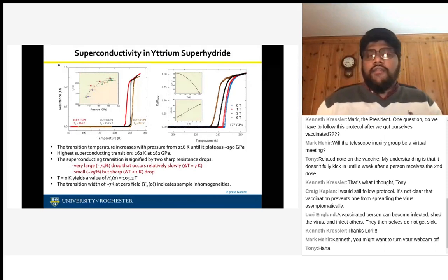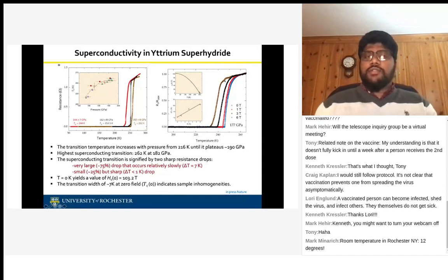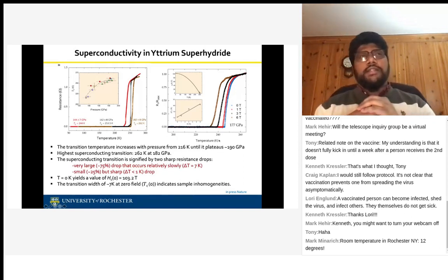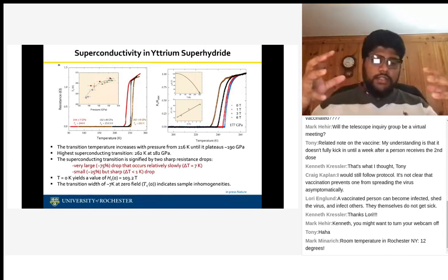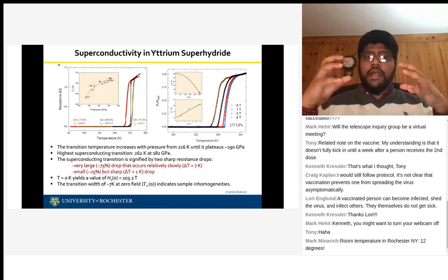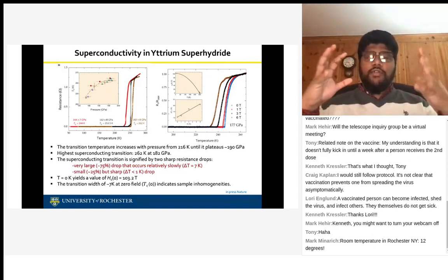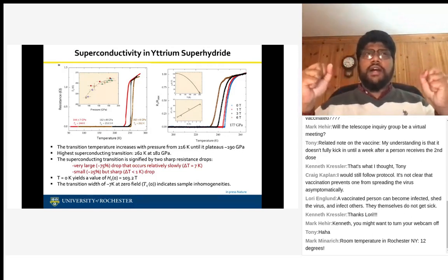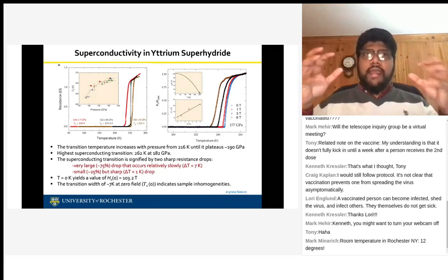What you're seeing in this graph on the right is that you apply a magnetic field of 0 Tesla, 1 Tesla, 3, 6 Tesla. You see that your transition is pushed towards lower temperature, which indicates that you're going through a real superconducting transition. So this gives you another indication that you're observing a superconducting transition. Another way of verifying this is another property of superconductors, the isotope effect. Because the superconducting mechanism is based on electron-phonon coupling, which means how the whole lattice vibrates, if you replace hydrogen with deuterium, your vibration is different now because it's a heavier atom.